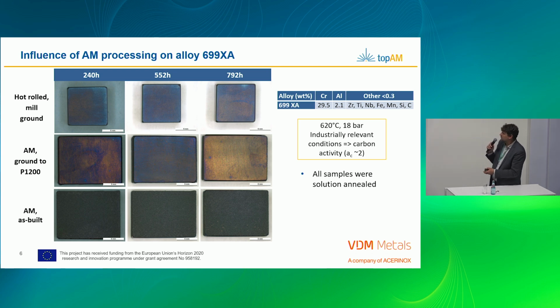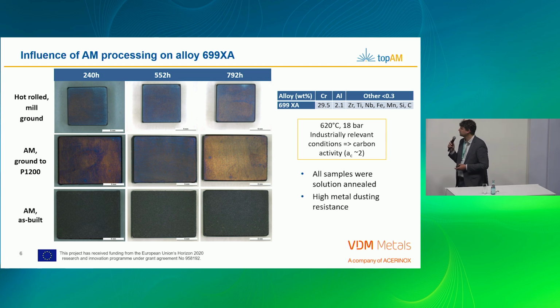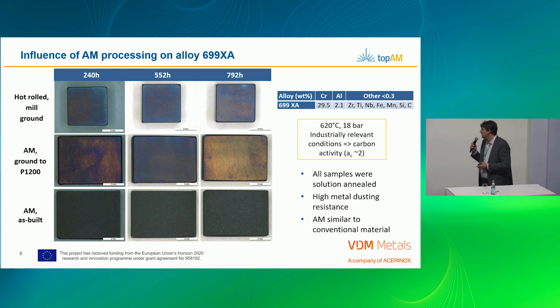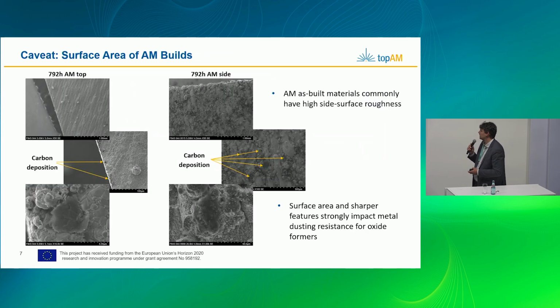So they build it. Here you can see that the surface on the bottom is the as-built surface, of course rough. After exposure, still we don't see much attack. Above that, the same when we have them just ground to 1200 grit. And on the top is the conventional hot rolled mill ground material. So generally, the AM is good, obviously, for metal dusting resistance. And from the alloy point of view, it's similar to the base material, to the conventional.